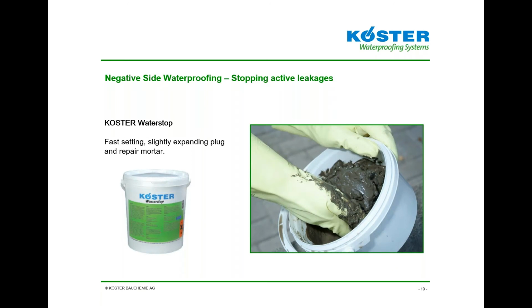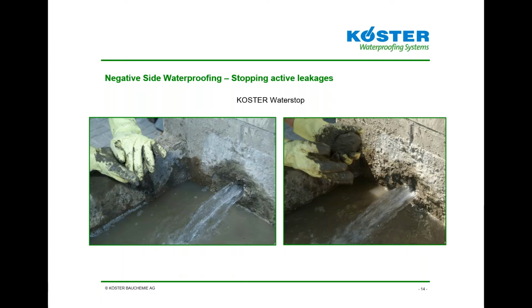Here we have the KOSTER water stop, which is a fast setting, expanding plug and repair mortar. This is more of your hydraulic cement with about a 30 to 40 second reaction time. So you mix this with water. For single source leakages and for things that are more oddly shaped, this is easier to form the material into a ball or the shape that you need and force that into place before it reacts. Again, it's an expanding repair mortar that's used for these active leaks. So we'd mix the material and turn it in hands to work the material.